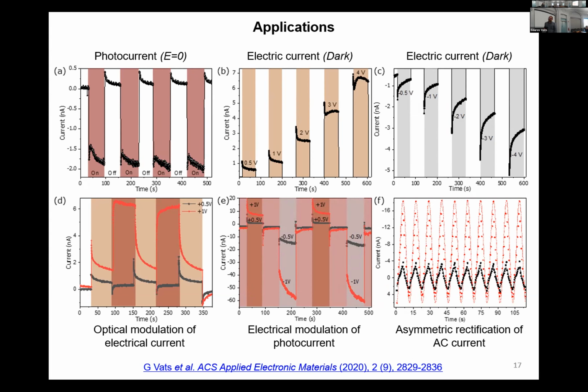So in this figure D, what I did is I started in dark. I applied a voltage of +1, it goes here. And on shining the light, it goes up. And I repeated that, but with a lower voltage of +0.5 volt, it was here. And on shining the light, it went in the opposite direction. So you can actually stop the flow of current by doing this. So this is very interesting because that could be used as a diode or some other application. In this case, I have only shown modulation of photocurrent. So there was a photocurrent which was modulated by applying positive and negative bias. And you can see the modulation is asymmetric in the positive and the negative direction.